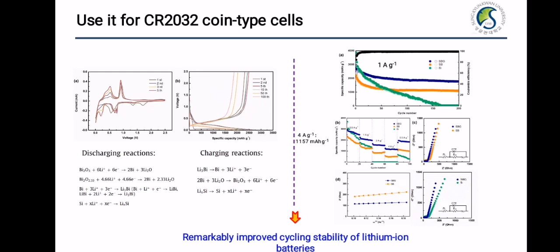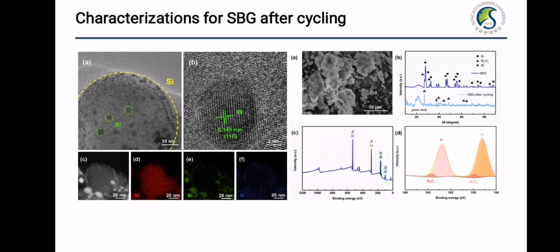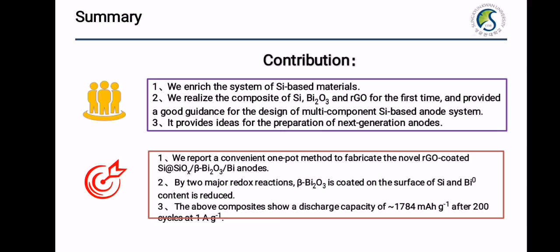Through the ex situ characterizations of SBG after cycling, we found that the bismuth content was increased while the bismuth oxide content was decreased. This phenomenon matches well with the results of the CV test. So in this work, our contribution is that we enrich the system of silicon-based materials, and we realize the composite of silicon, bismuth oxide, and reduced graphene oxide for the first time, and provide good guidance for the design of multi-component silicon-based anode systems. And it provides ideas for the preparation of next generation anodes.